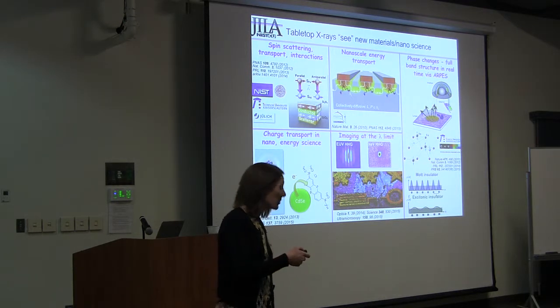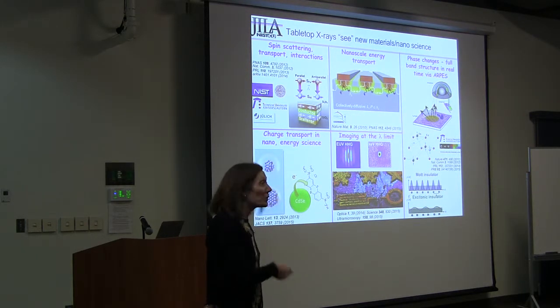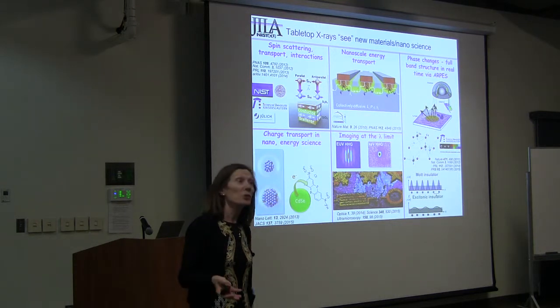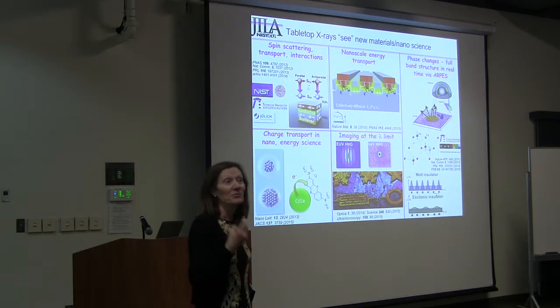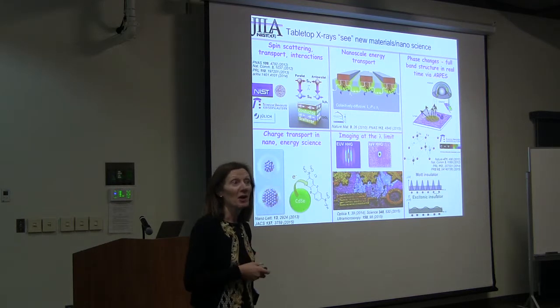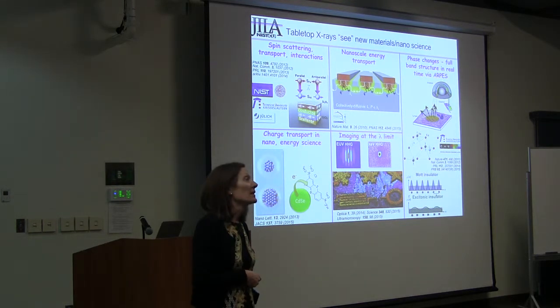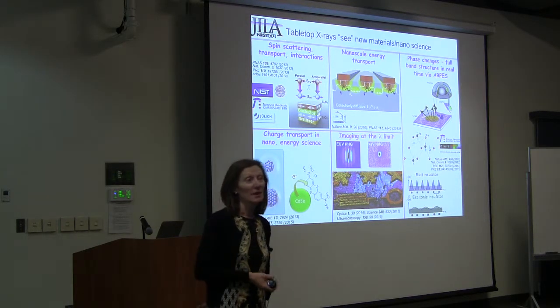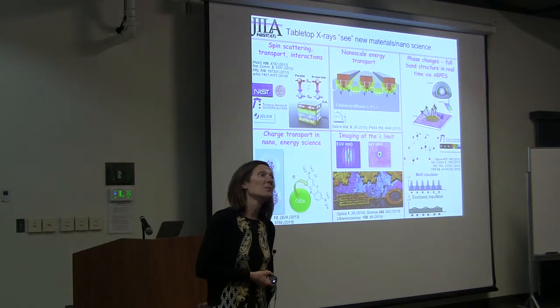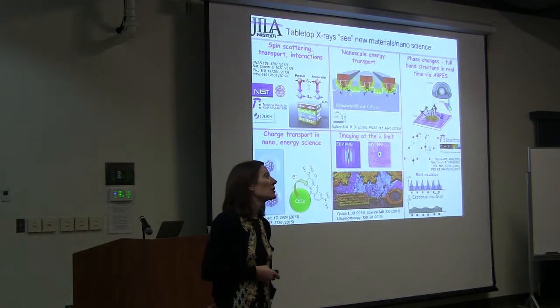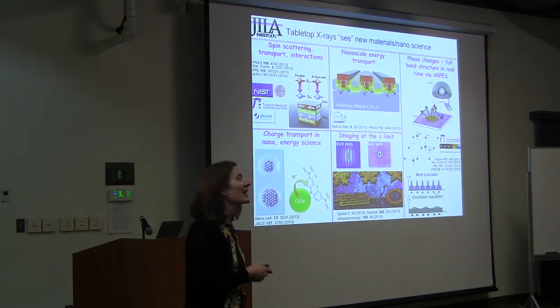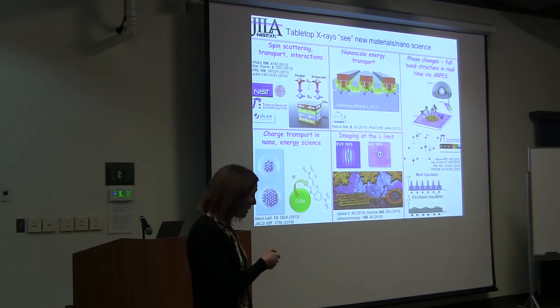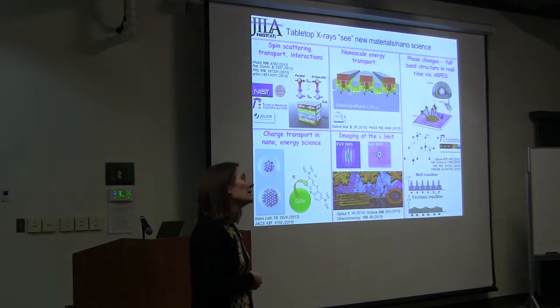And in addition, we also get to do things like single photon photoemission, since, for example, the 29th harmonic of Ti:sapphire is at a photon energy of about 42 eV, well above the work function of any material. So you get beautiful photoelectron spectra using harmonics. And in fact, this is one of the killer apps. I won't talk very much about it, but it is one of the killer apps because it is the one application where we always have too much high harmonic flux.